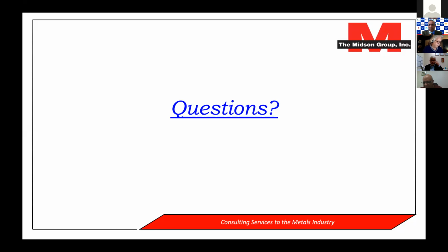Well, that's a good question. And again, we don't really have data on that. The caster that was doing this trial, we've talked to some of their engineers over there, and we asked them, how long do these coatings last? And they say as long as the die. And certainly, the fact that we are still able to produce castings at a low lubrication level suggests that the coating is still in place in this die. But we have not done a rigid test to see exactly how long coatings last. So I don't have good data on that, but they do seem to be lasting quite a long time.